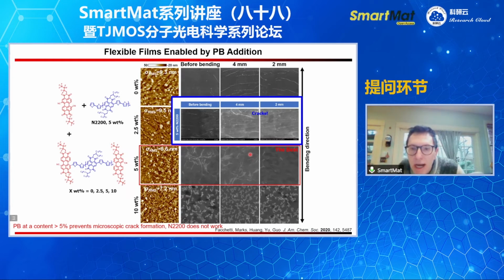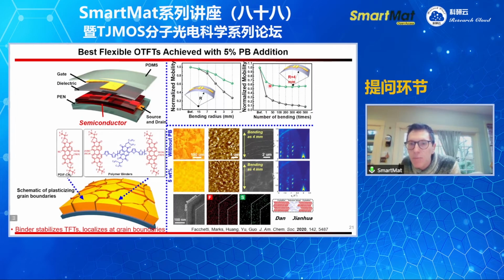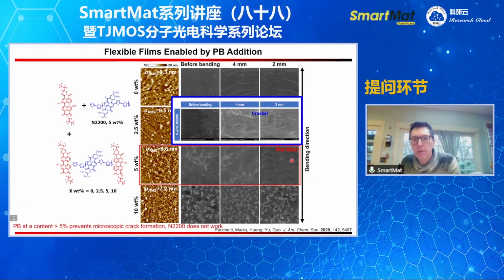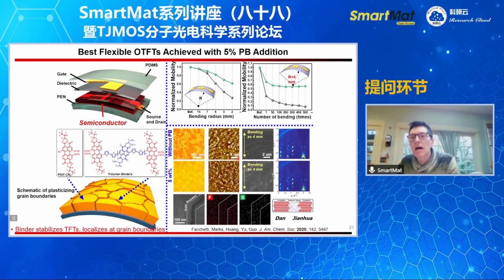Probably you see here, right? There's a couple of points where you can still see some cracks. So at the beginning, the mobility also drops a little bit, but then after these cracks form, the other grain boundaries are stabilized, and the performance does not change anymore. Yeah. So I think this is quite good evidence, combining this experiment with this experiment, particularly the control experiment. It tells you the importance of the molecular design of the binder.